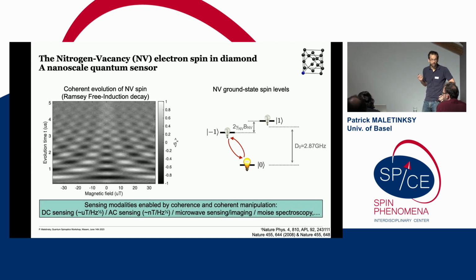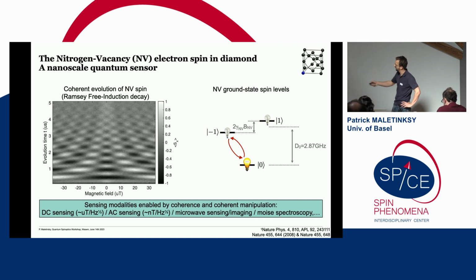We can also do coherent manipulation of these spins, and here I show you an example of a Ramsey free induction decay, exploiting one of these two-level submanifolds here. What we do for these experiments is to initialize into this ground state, create a coherent superposition of this two-level system, and then let this evolve over time. And you see how here with time, you accumulate a quantum phase. And as you change detuning, and I express this here in units of magnetic field, of course, there's also a beating. And this is another way of understanding how we can do magnetometry using quantum manipulation of the NV spin.